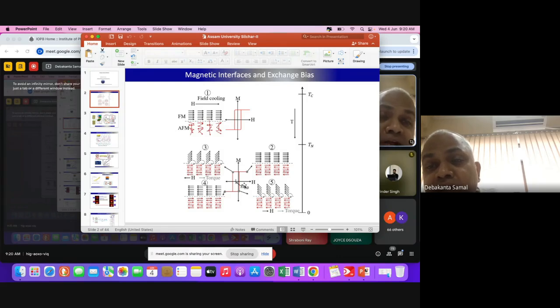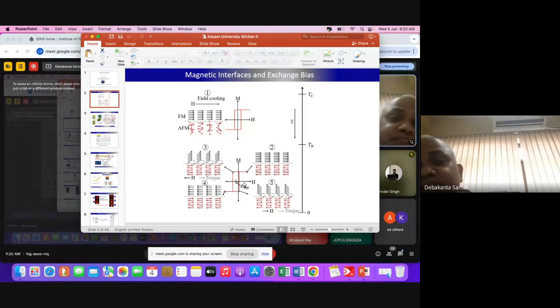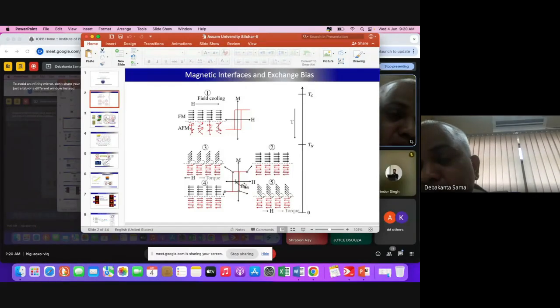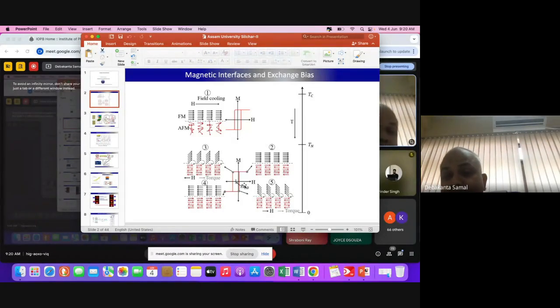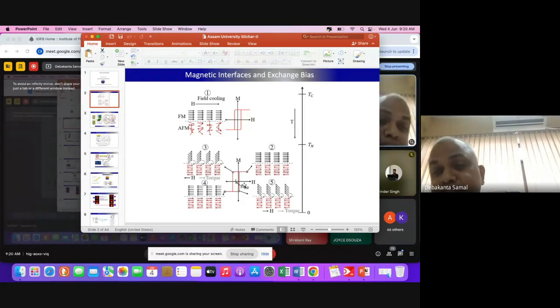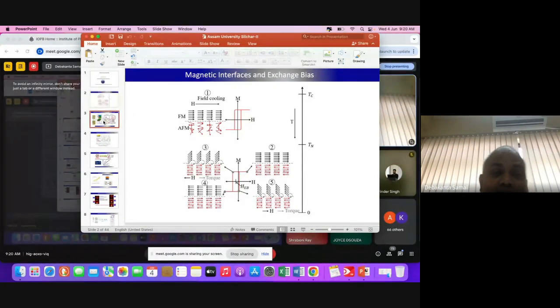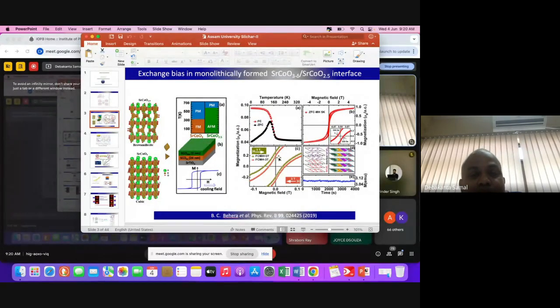So what is the important point of exchange bias? The hysteresis loop shifts in a particular direction. A simple, single ferromagnet will not do this. But you are introducing an interfacial coupling between the ferromagnet and the antiferromagnet. You see how the manifestation is: the loop is shifting. In this regard, we have done various work; I do not want to get into detail. You see here in figure C how the hysteresis is shifting from one to another. So this is a very important point to look into: how the hysteresis shifts in a ferromagnet-antiferromagnet system.